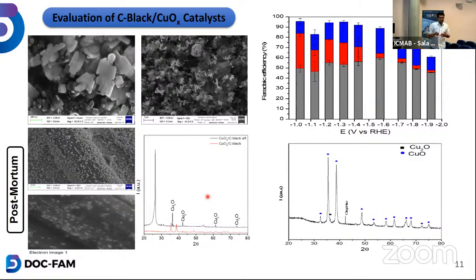Technically, it is not completely reducing the copper oxide to metallic copper, because the potential we are applying is acting on the electrolyte, on the membrane, on the whole system, and not only on the working electrode or the cathode. So there is some internal resistance as well. So what we could see even after the electrolysis was some amounts of copper oxide, copper 1, I can say.